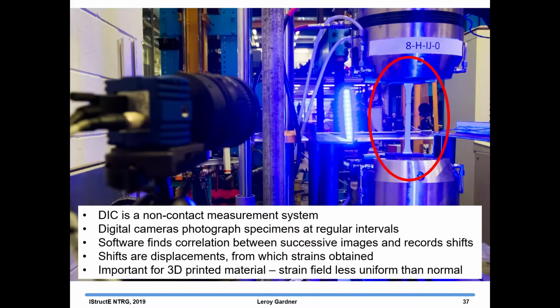So digital image correlation is a non-contact measurement system. Basically, digital cameras are used to take photographs of the specimens at regular intervals. Software is then used to track the movement of the dots in successive images, and these shifts that it detects are displacements, which can then be converted into strains. And this measurement technique is particularly useful for 3D printed material because the strain tends to be less uniform than ordinary produced material.